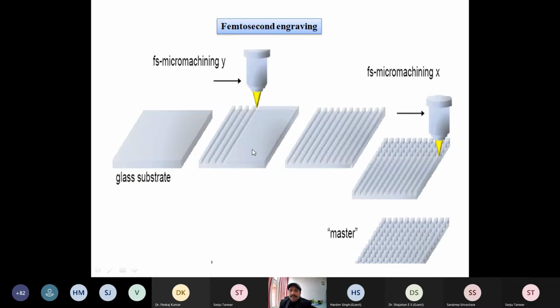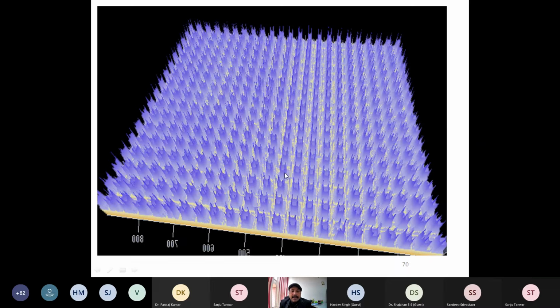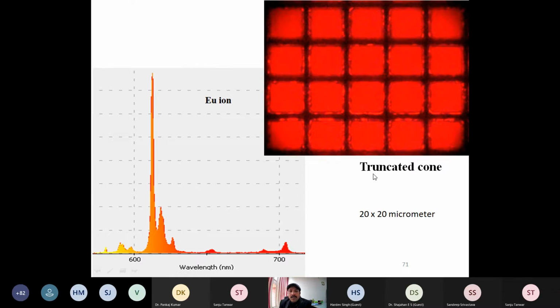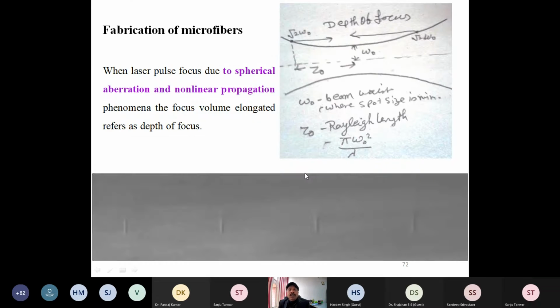So you have one glass substrate and you can scratch some lines into it, and then this type of structure. We use a polymer coated glass slide here that is doped with europium ion, and you can see this type of structure. The advantage is you can control the width, because you can confine the light, and here we are getting only 2 to 3 nanometer thickness of europium emission.